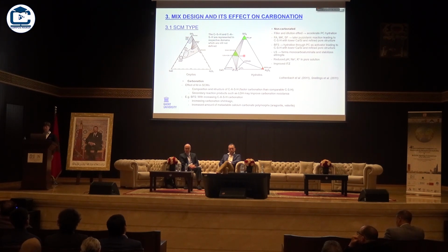the Portland cement hydration. And then when you add SCMs like fly ash, metakaolin, silica fume, blast furnace slag, they go into a latent hydraulic or pozzolanic reaction in the second step, and you get more CSH with a lower calcium silicon content, but also a refined pore structure. Additionally, you will get a reduced pH because you bind portlandite, and reduced sodium and potassium contents in the pore solution, and we also often see an improvement of the interfacial transition zone between the paste and the aggregates.